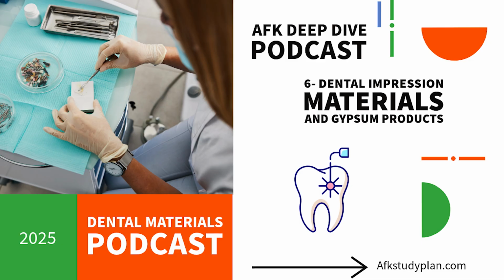What's type 4? Type 4 is high-strength dental stone, or die stone. It's a modified alpha hemihydrate. Even more regular, denser particles, needs even less water. So it's very strong, very hard, and doesn't expand much. Ideal for making dies for crowns and bridges. Exactly. High accuracy, high surface hardness, resists scratching, minimal expansion are crucial for dies.